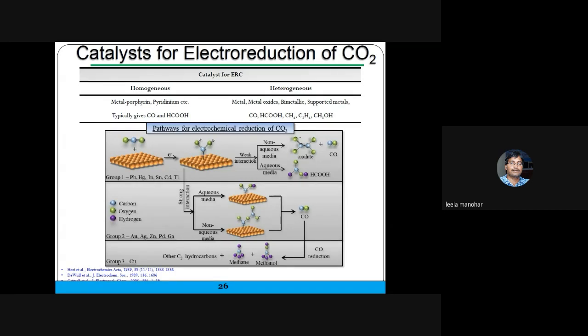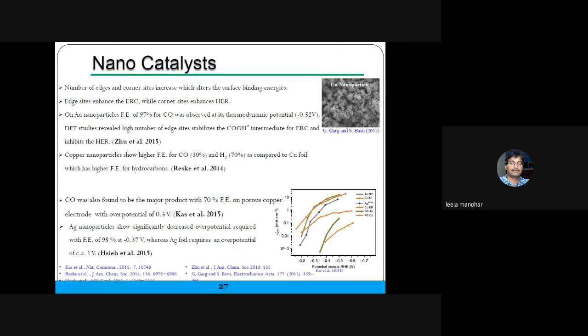They developed copper nanocatalysts, copper-based alloys, copper-derived catalysts. If you see in a nanocatalyst, the number of edges and corner sites is increased, which alters the surface binding energies, and it may also enhance the hydrogen evolution reaction. Some gold nanoparticles may give carbon monoxide at 97 percent. Some other copper nanoparticles may show higher Faradaic efficiency for carbon monoxide, which is 30%, and hydrogen, which is 70%, compared to copper, and copper shows the higher Faradaic efficiency for the hydrocarbons.